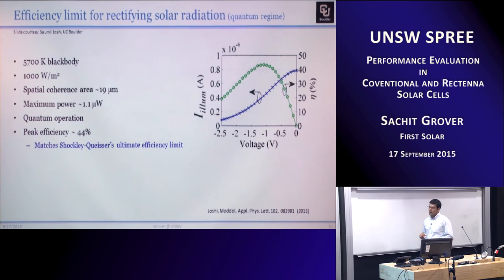The question that arises in the field of rectennas is how high in efficiency can they go? Because again, as I started out mentioning, classical rectennas can go up to 90%. So why are these limited to 44%? Well, the theory points to a similar efficiency limit as a classical semiconductor-based solar cell. And that's because, again, your operating point is fixed in voltage. Even though you have a full spectrum coming in, you are operating at one particular voltage. So all the photons that were above that voltage have to go through an energy loss, thermalization, to be at that operating voltage.